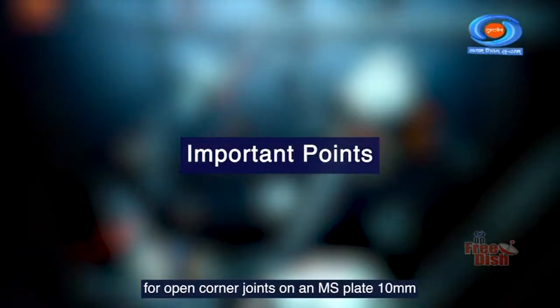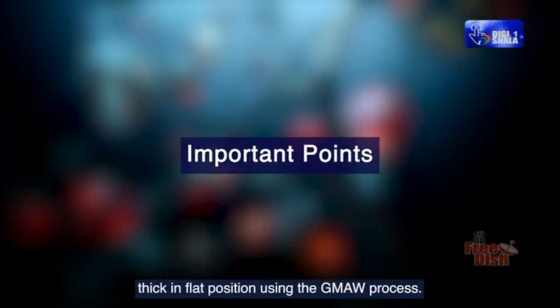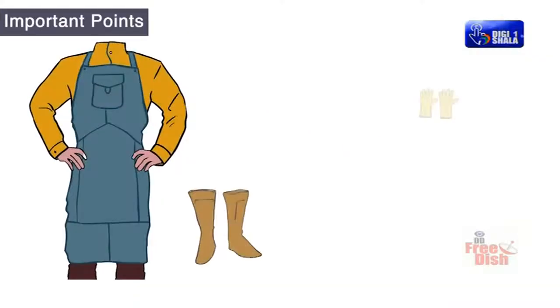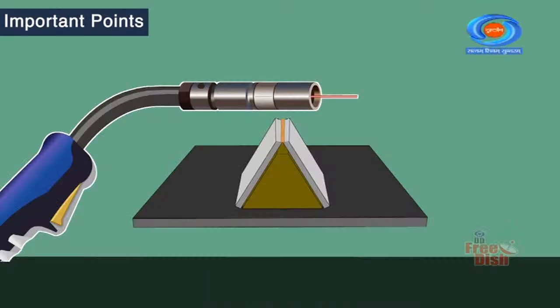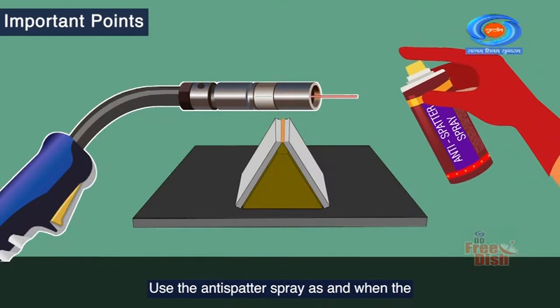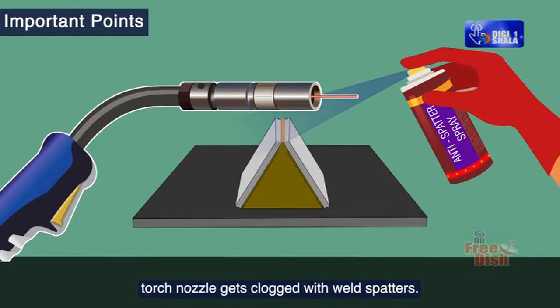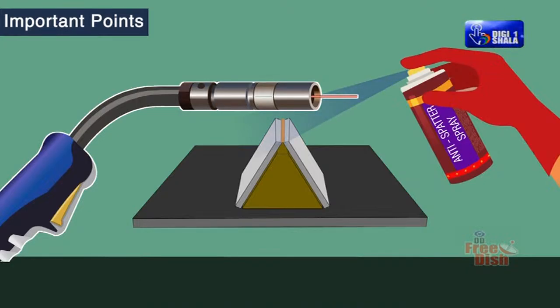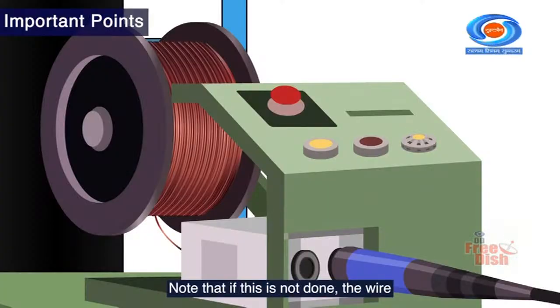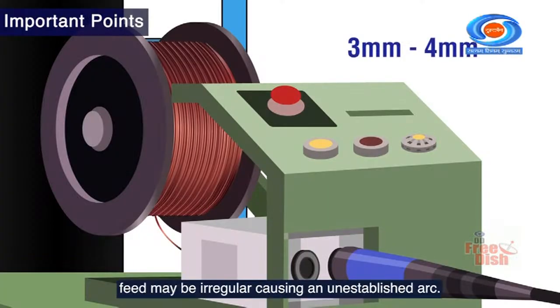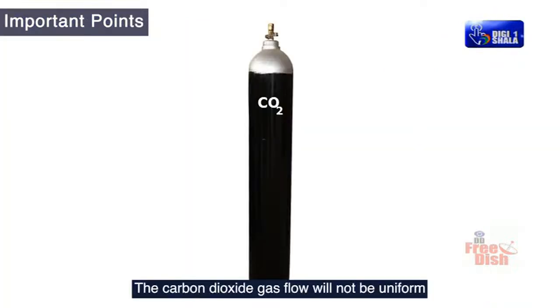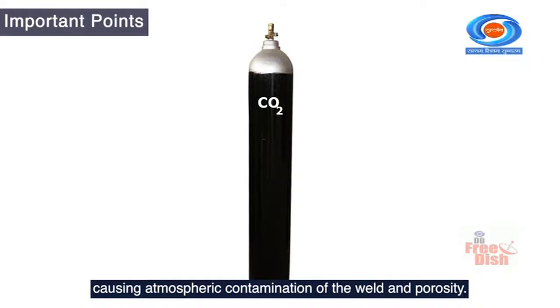There are some important points to be followed for open corner joints on an MS plate 10 mm thick in flat position using the GMAW process. Wear protective clothing. Use the anti-spatter spray as and when the torch nozzle gets clogged with weld spatters. Note that if this is not done, the wire feed may be irregular, causing an unestablished arc. The carbon dioxide gas flow will not be uniform, causing atmospheric contamination of the weld and porosity.